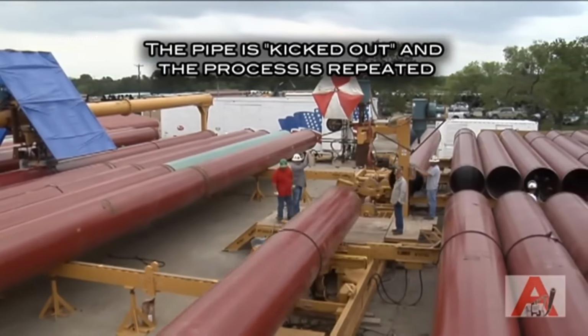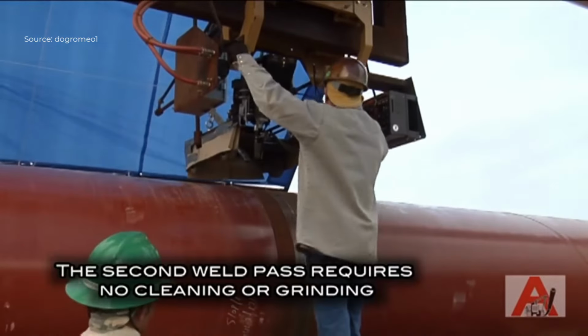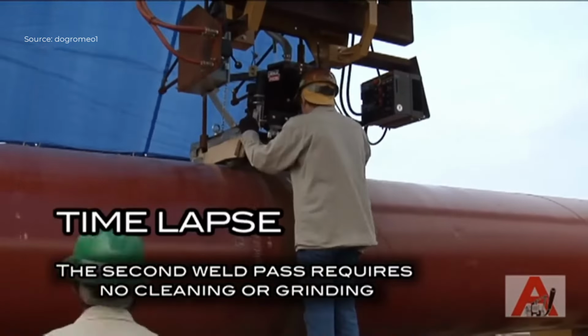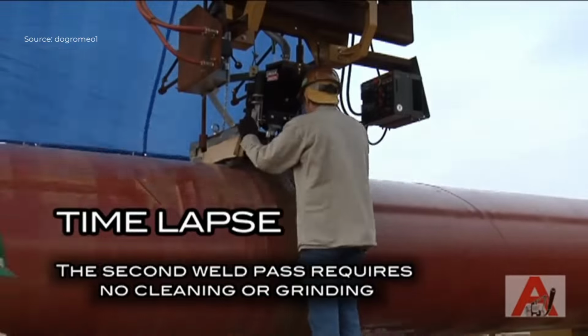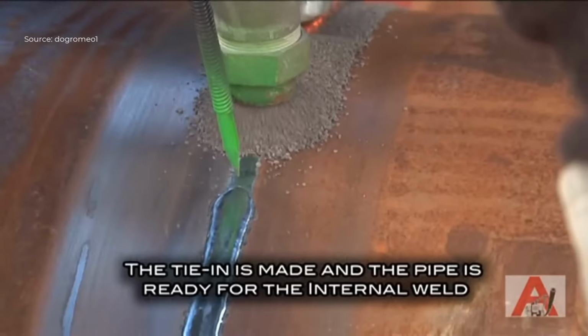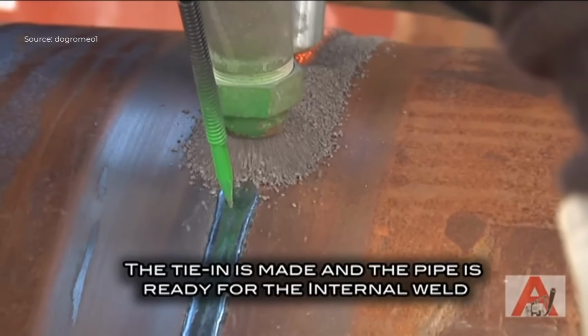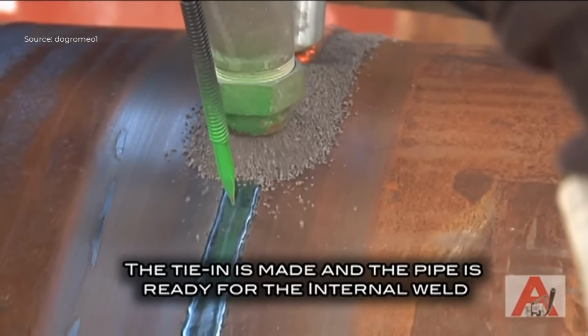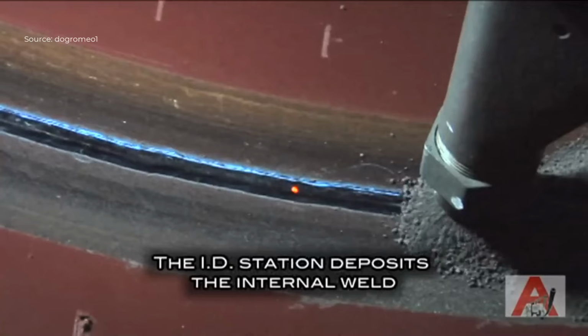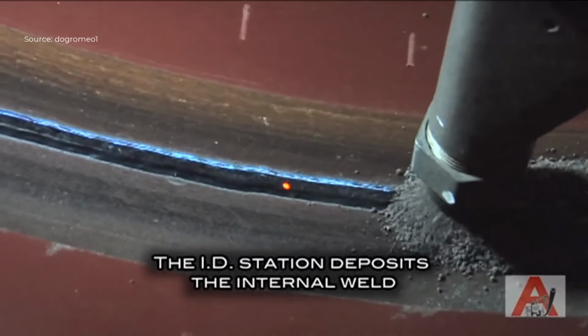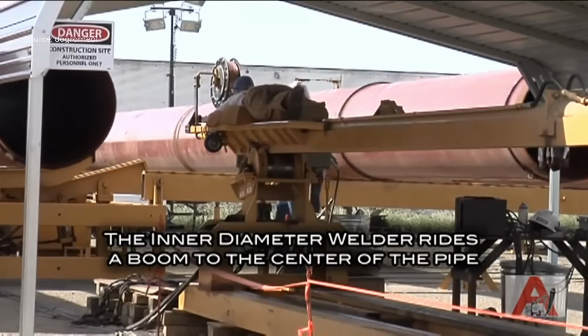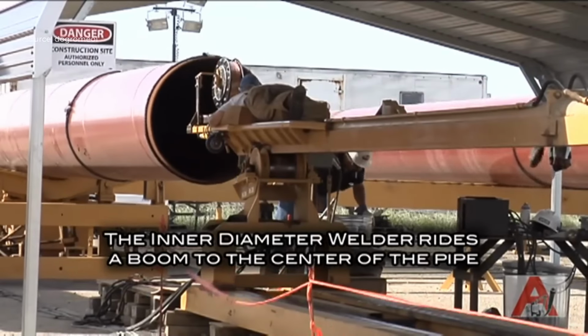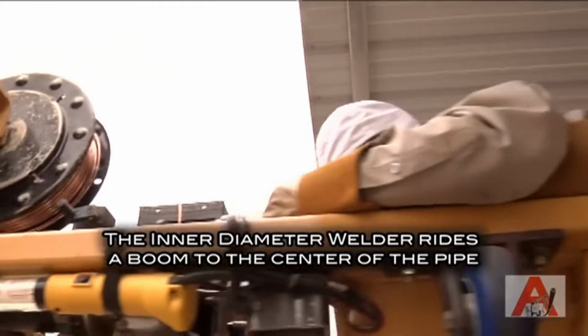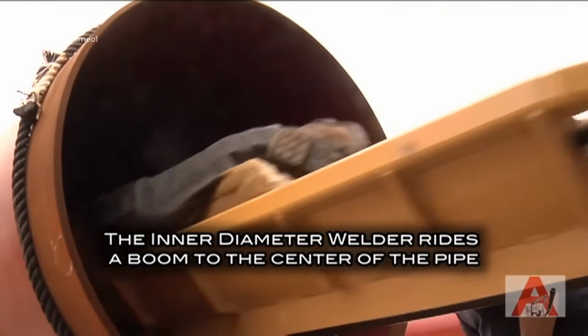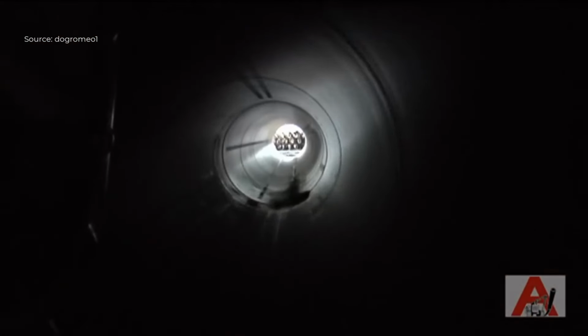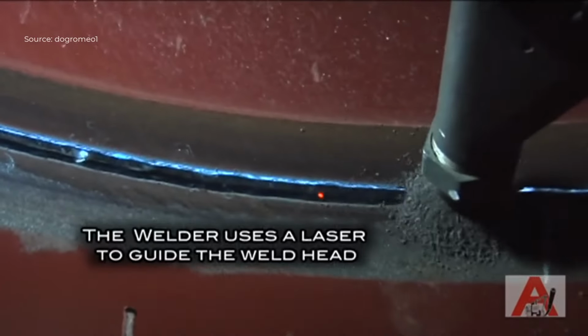Next, at the outside diameter 2 station, the cap pass is applied. This second weld pass strengthens the joint and requires no further grinding or cleaning. The pipe then moves to the internal diameter welding station. Here, the internal welder, mounted on a movable boom, travels to the center of the pipe. Using a laser guidance system, the welder performs the internal weld pass, ensuring perfect penetration and alignment. After welding, a cleanup worker enters the pipe on a cart to remove any flux and slag residues.